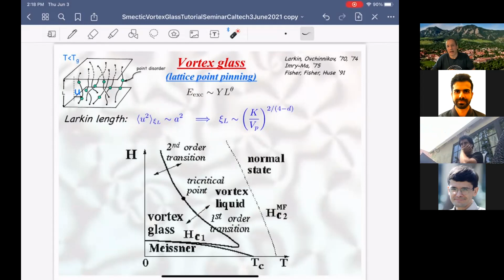And so because of that, you can get to a system length, which we call the Larkin length. And that length is finite if you're below 4 dimensions for point disorder. Below this length scale, the system looks ordered and crystalline, but beyond this length scale, it crosses over to its asymptotic state, which doesn't break translational symmetry. And of course, this is just a hint that a new phase may emerge. It's not a proof that there's a glass state.